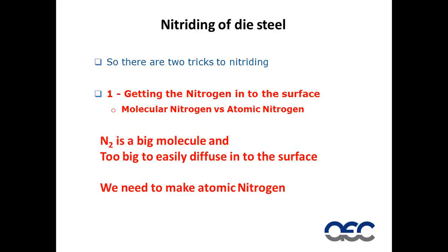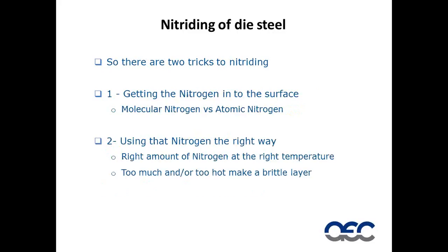So that's the first trick in getting nitriding to work, the creation of atomic nitrogen to diffuse into the steel. The second trick, once we've got that atomic nitrogen, is using it in the right way, getting the right amount of nitrogen and at the right temperature. As Paul has said in his super extruder paper all those years ago, everything is about temperature. Well, guess what? Nitriding is also about temperature. So we need the right amount of nitrogen in the right place at the right temperature. Too much or too little, we end up with it being either brittle, as you saw in those pictures of it cracking and flaking, or we don't make the die hard enough and we've just been wasting our time. So we really need to get the balance right in the amount of nitrogen and the temperature at which we get that nitrogen into the surface of the steel.